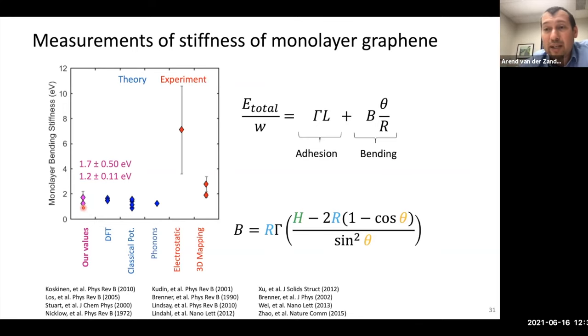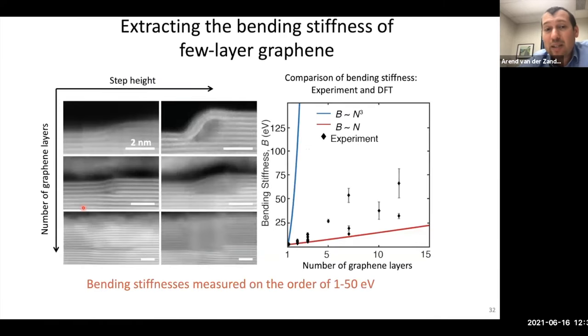Monolayer graphene is easy. We actually had a pretty good idea of what to expect for it. What is less obvious is, when you have a multi-layer stack, how do these layers interact and how does that affect the bending stiffness? So to study that, we changed the number of layers in the graphene and we changed step height and we just measured many, many different devices.